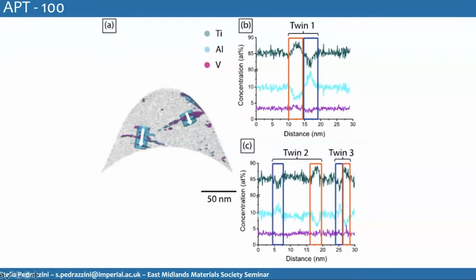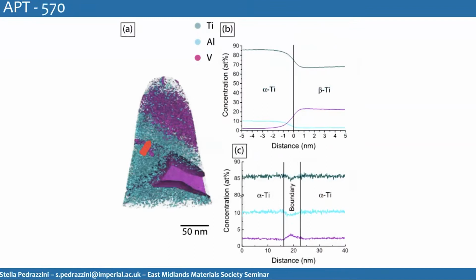So at 100 degrees, looking at the twins that were there, we can see an excess of titanium and a reduction of aluminium and a bit of vanadium at the twin boundaries. So this is quite interesting. There is some segregation at the twin boundaries. At 570, clearly we've dissolved the twins. We've got rid of them through heat treatment at higher temperature. And looking at the dislocations here, we see the same type of segregation, the same kind of thing of excess vanadium and titanium depletion.